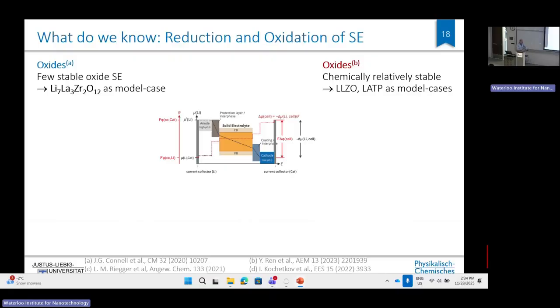Okay, and that brings me to summarize the stability issues. Let's look to the left side. So the oxides, in fact, we found only, I would say, the garnet oxide really is stable. That's why companies worldwide explore this material as a separator material. The problem is to make thin, 10 micron thin, large scale area separators, ceramic separators, cheap and pinhole free over square meters. This is a pretty tough subject. QuantumScape in the US, I think, is trying that since years. And you probably can see the shares of QuantumScape, whether they will be successful or not with that enterprise.